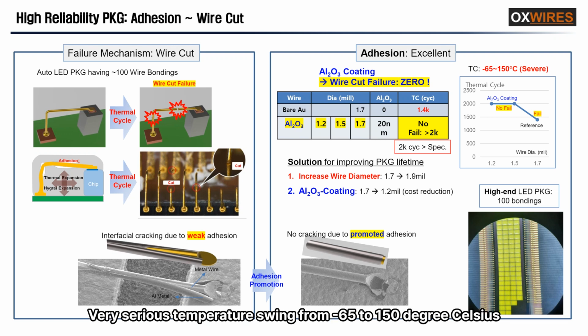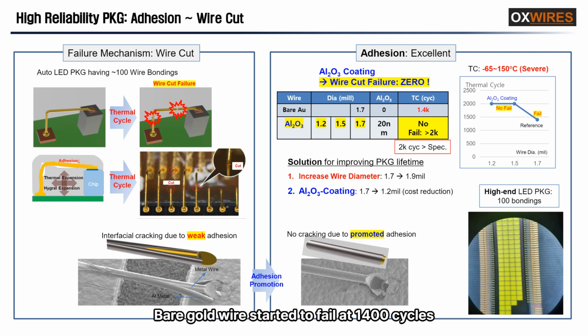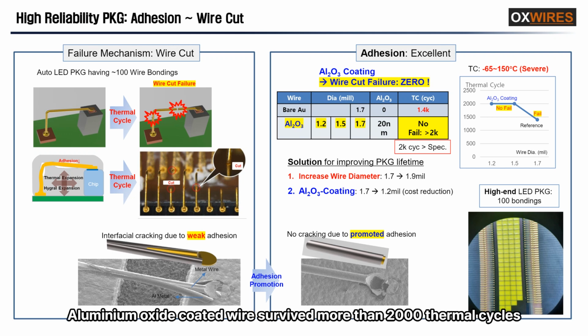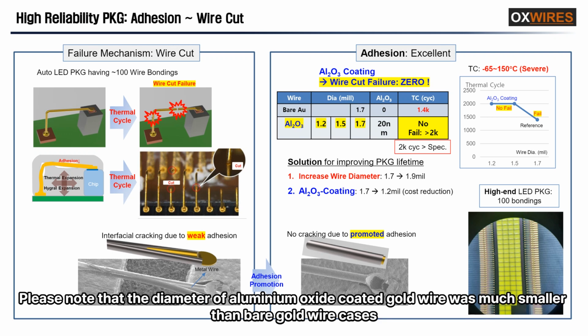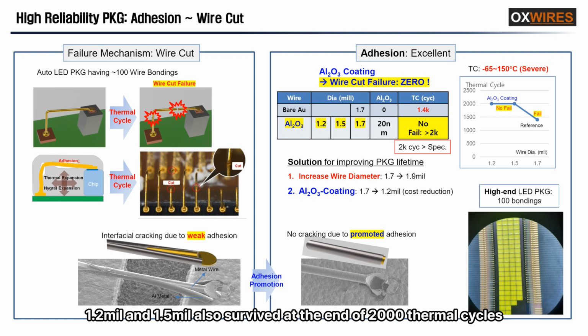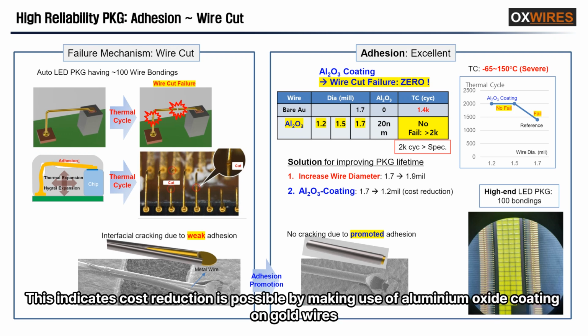Very serious temperature swing from -65 to 150 degrees Celsius. Bare gold wire started to fail at 1400 cycles. Aluminium oxide-coated wire survived more than 2000 thermal cycles. Please note that the diameter of aluminium oxide-coated gold wire was much smaller than bare gold wire cases. 1.2 mil and 1.5 mil also survived at the end of 2000 thermal cycles. This indicates cost reduction is possible by making use of aluminium oxide coating on gold wires.